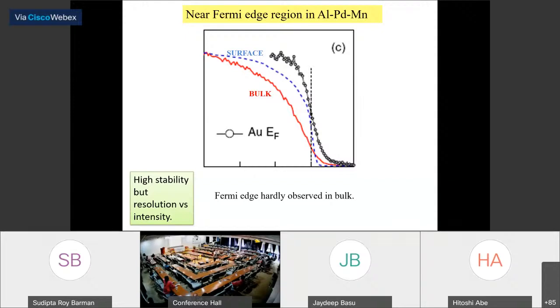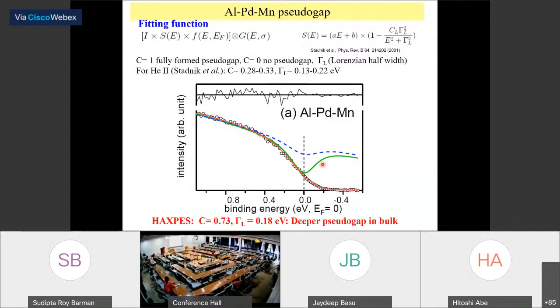And this is the Fermi edge of gold, and you can see that between even the bulk and the surface, there is a difference in the spectral shape. So we looked at this spectral shape very carefully, and we do all different kinds of data analysis and extract the shape of the suppression. If you see the blue curve here, this is what was measured by low energy photoemission, helium 1, helium 2, and this is what we measured using hard X-ray photoemission. So this showed that the shape of the pseudogap, which is much deeper than what is at the surface, can be probed by hard X-ray photoemission.